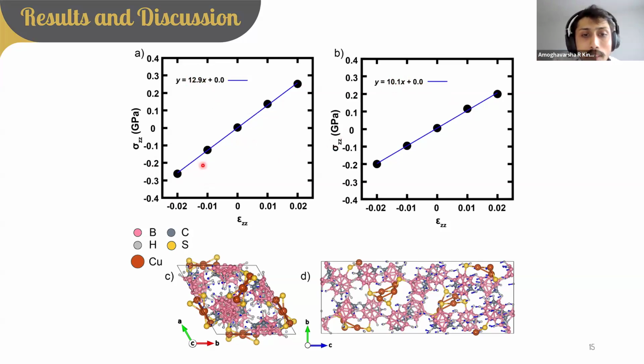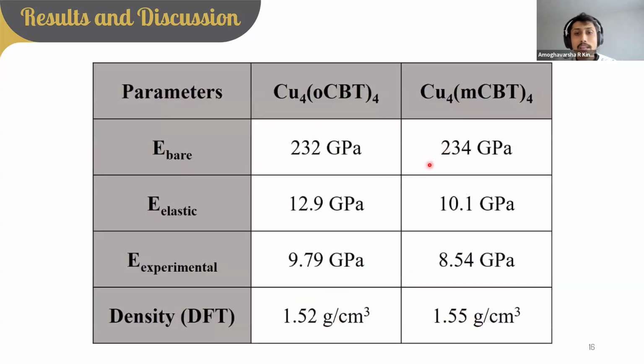Now, the linearity of this graph indicates that as we apply the strain, the stress falling upon the crystal is following Hooke's law. And in the case of these values, also we can see that copper 4 OCBT is showing slightly more stress upon its structure than copper 4 MCBT. To summarize this computational study, the E bare, which I defined as the Young's modulus of the unrelaxed structure, we can see that the Young's modulus is 232 gigapascal for copper 4 OCBT and 234 gigapascal for copper 4 MCBT, which is following the normal trend that a highly dense material has a higher hardness or higher Young's modulus. But when we allow the structure to relax, there are certain mechanisms of relaxing in both of the clusters which are different from each other.